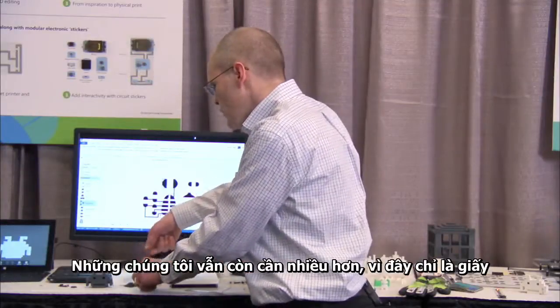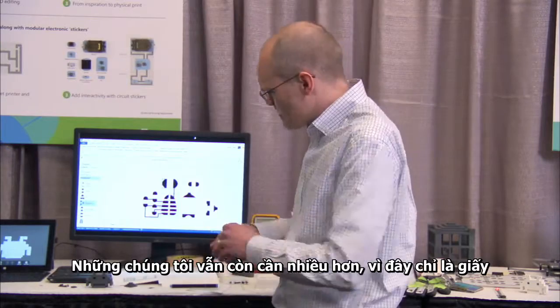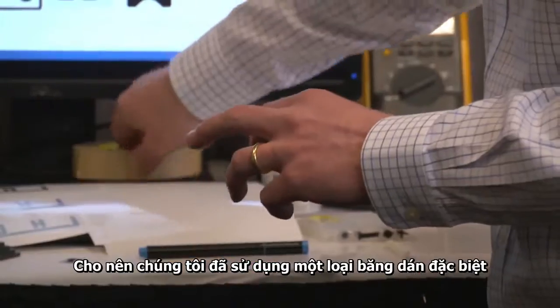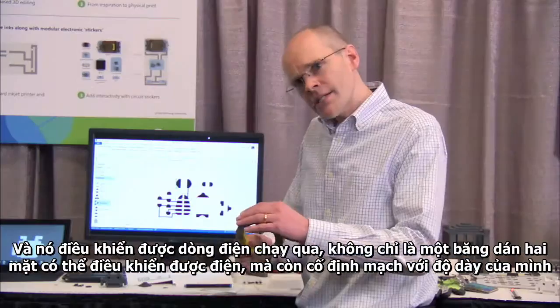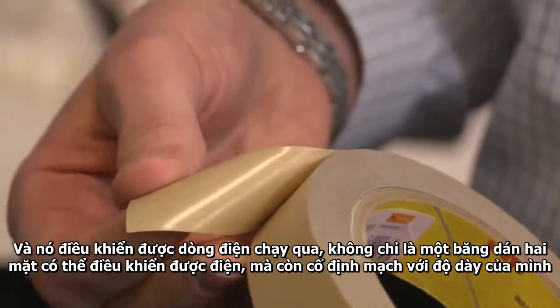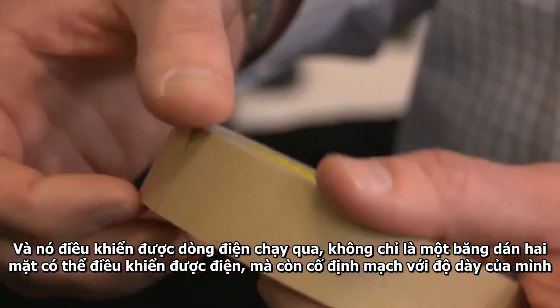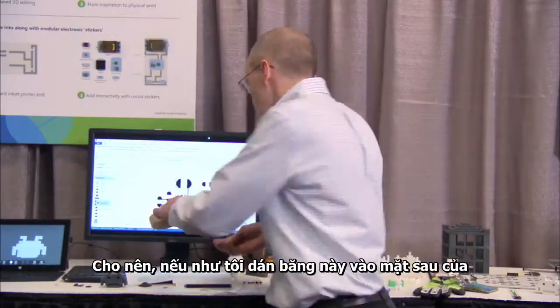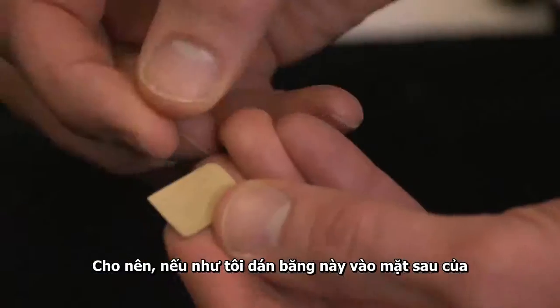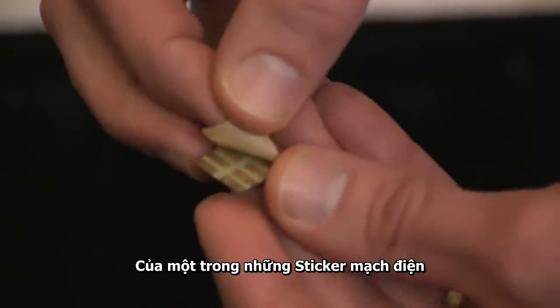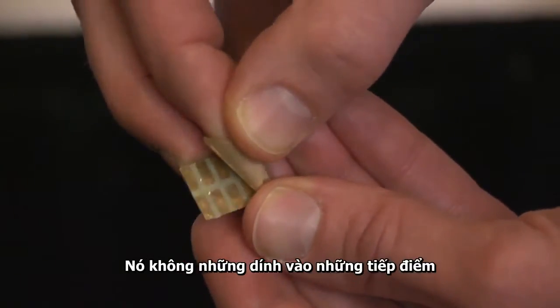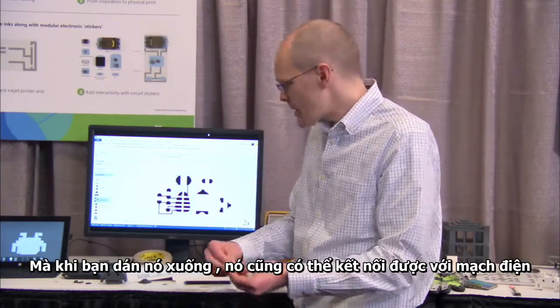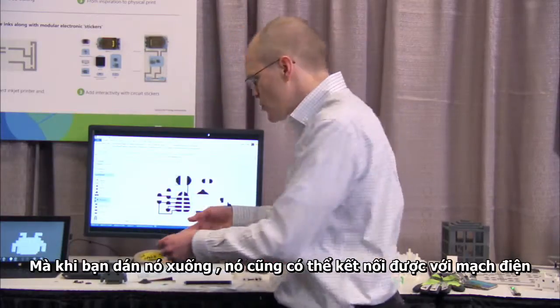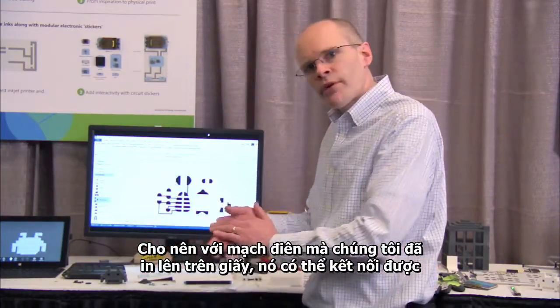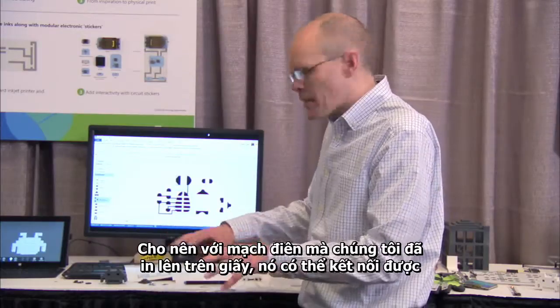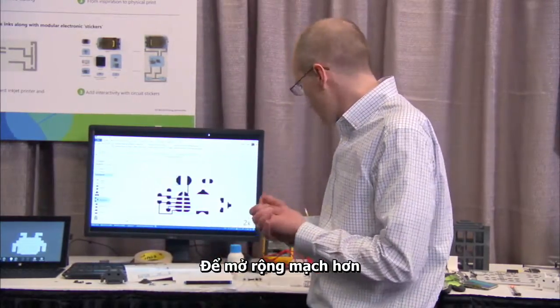But we still need some way of attaching these, and we can't solder to it because it's paper. So for that, we use a special type of tape made by 3M. It's electrically conductive double-sided tape, but it only conducts through its thickness, not across the surface of the tape. So if I put some of this tape on the reverse side of one of these circuit stickers, it doesn't short circuit these connection points, but when you stick it down, it's going to make a connection through. So the conductive circuit we've printed on the paper acts to wire together your circuit.